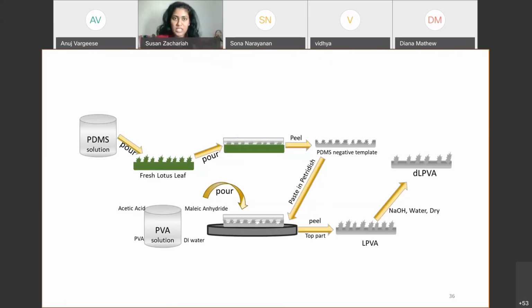But for pervaporation, we need to get a hydrophilic membrane. Once we get these patterns, as we already discussed, it becomes hydrophobic. Why we did this is to get good mechanical properties, but to make this hydrophobic PVA more hydrophilic, we deprotonated it using NaOH, and finally we got a membrane with lotus leaf patterns and hydrophilic nature to use for salt water or seawater desalination. This is the process which we have used. Since this is in a review stage, I'm not discussing much about this work.